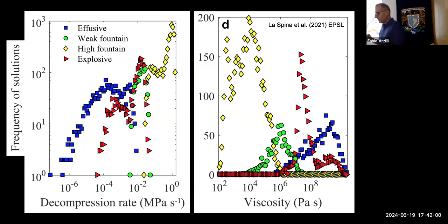Now, if a magma is able to reach the surface feeding an eruption, what we observed during 10,000 simulations with the basaltic magma, considering disequilibrium in crystallization and vesiculation during magma ascent, is that the decompression rate and viscosity control the eruptive style. So a very slow decompression rate, the blue one, will promote effusive eruption with basaltic magma. If we have a faster decompression rate, we can associate it with ascent rate in some way. So we can promote highly explosive eruption, the red one.